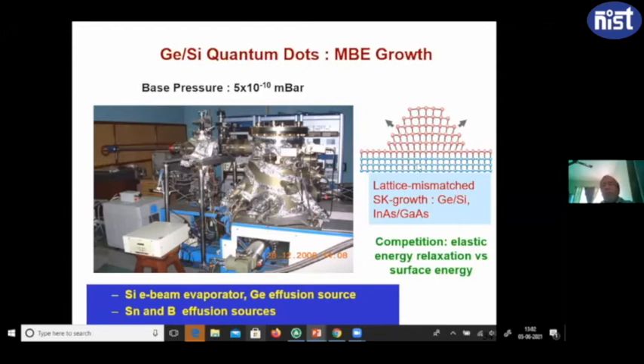If you grow germanium on silicon, due to the lattice mismatch of germanium and silicon, as I showed you earlier, they try to grow as islands after some thickness. And if you stop the growth at low temperature after a certain thickness, you get this germanium nanocrystal and germanium quantum dot. So this is purely the beauty of material science. And it is necessary that if you grow new materials, only then can you use nanofabrication technology